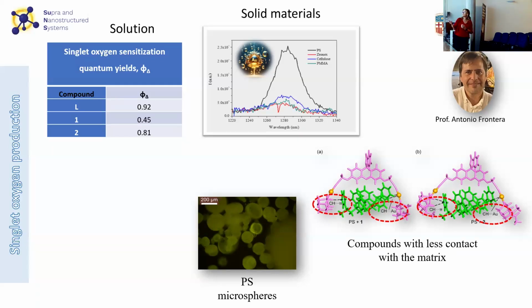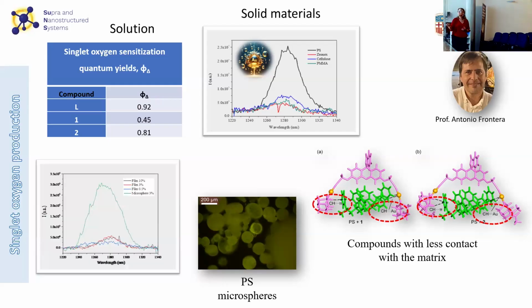And in these cases, we synthesized these polystyrene microspheres. We can observe in these fluorescence microscopy images that the spheres were completely doped with our samples, since initially they are white, but in these cases they are displaying this yellow emission due to the presence of our compounds. And we measured singlet oxygen, and if this point here was this point here, now there is a clear enhancement just by increasing the surface of contact with the oxygen.